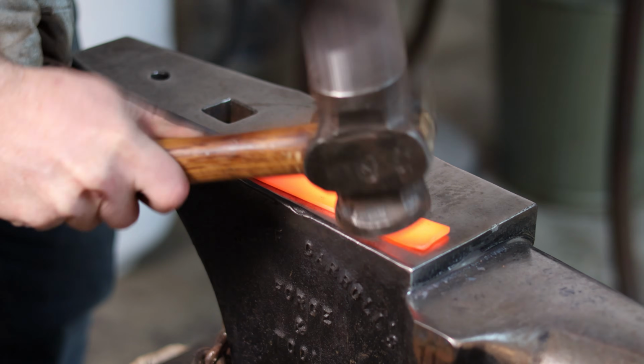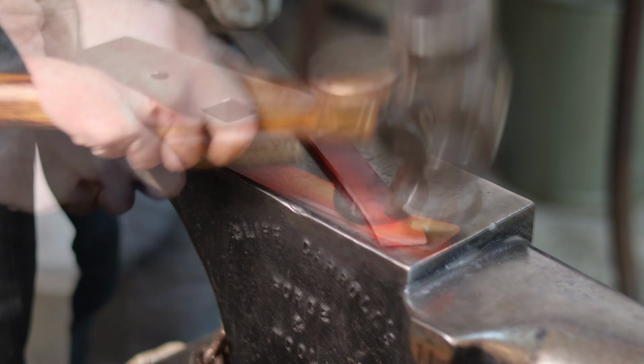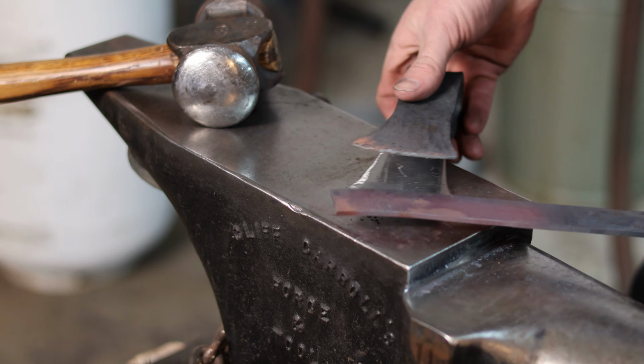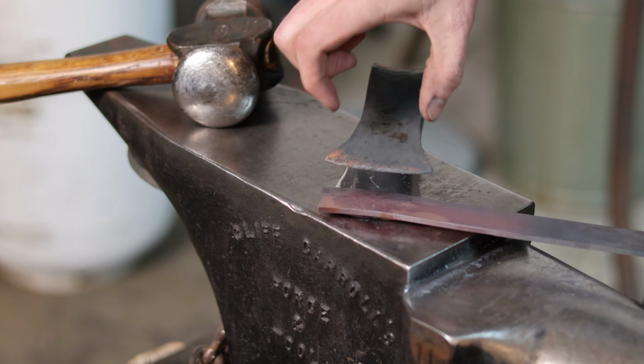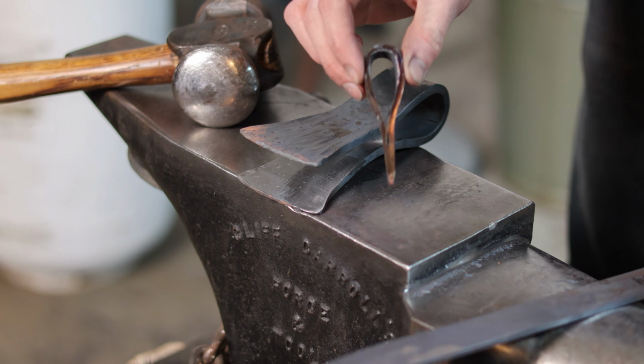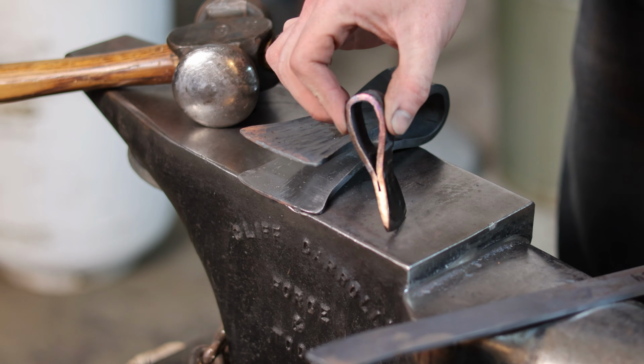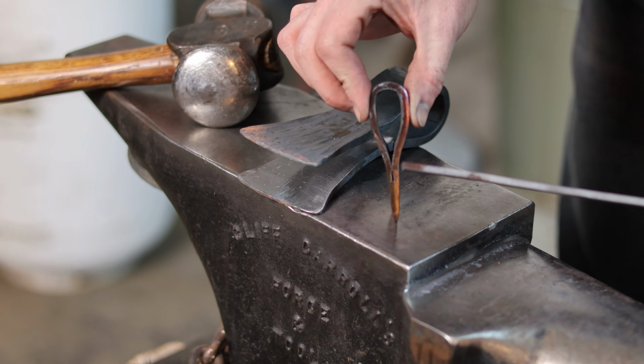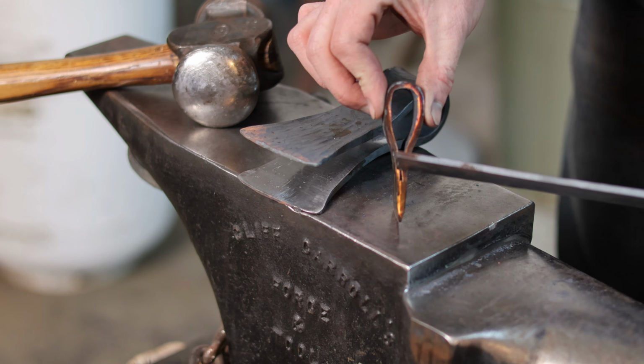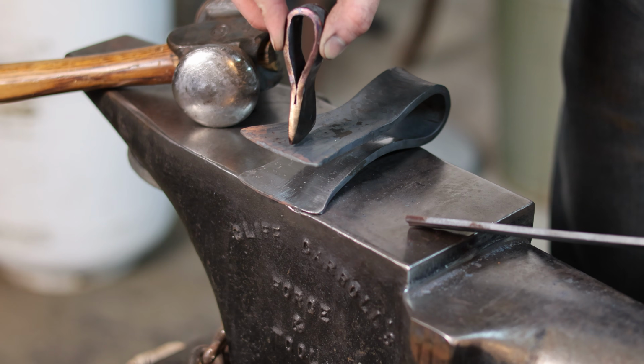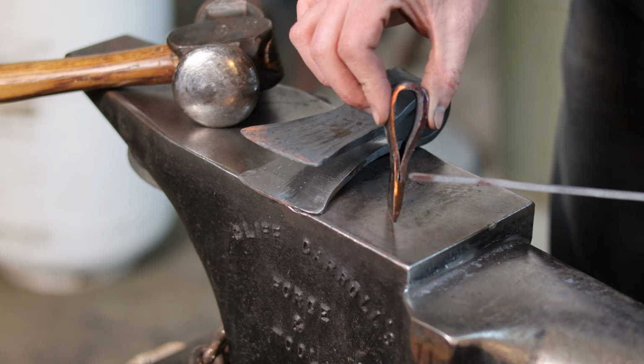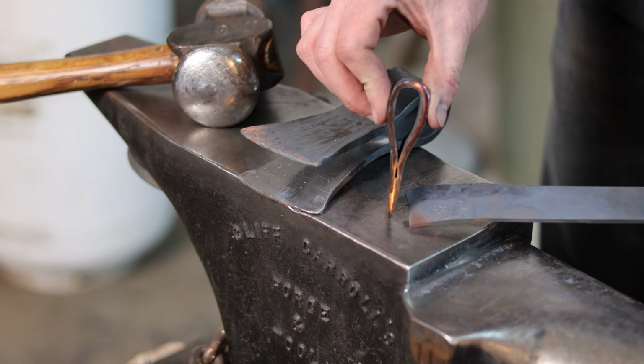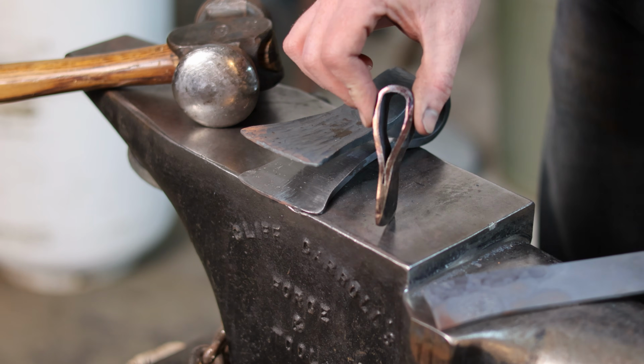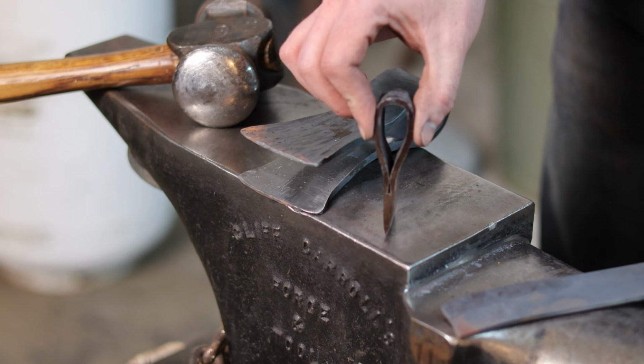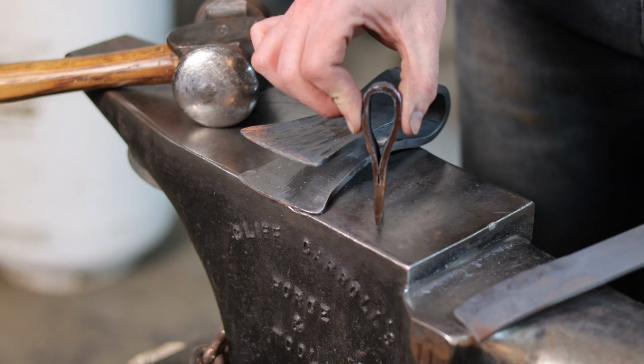And I'm thinning out this edge in order to forge weld this as a bit into the blade. And I learned in the process of making my tiny tomahawk that if you don't taper the bit that you're forge welding into the Tomahawk, that you'll have a gap. And that can lead to cracking and splitting of the blade if you're using it to chop or throwing it into hard wood over and over and over again.